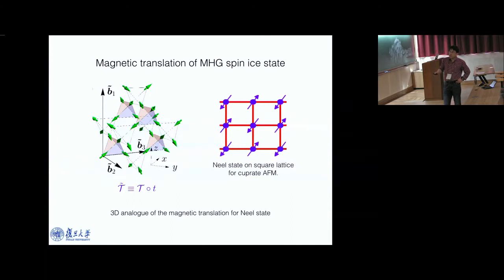Originally this tetrahedron is equivalent to this one, just by a lattice translation. This is identical to this guy, but because of the presence of magnetic order, this is no longer equivalent. Look at this spin. This spin is in, and this spin is out. So it's no longer equivalent. So the magnetic cell is twice larger than the crystal cell. But if you combine translation and time reversal, the system stays invariant. If you translate this unit cell, this tetrahedron, to here, and then do a spin flip, the system stays invariant. So the combination of time reversal and translation has been preserved.